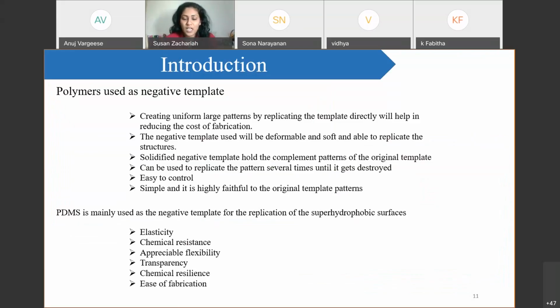To make a structure similar to the lotus leaf, first we need a negative template that can take the structures of the lotus leaf and give them to the polymer coating that we use for the cold rolled steel. A negative template takes the complementary structures of the lotus leaf. So if the lotus leaf has peaks, then this negative template will have holes. When we place this negative template on the polymer coating on the surface, we get the actual structure of the lotus leaf on the coating applied on the cold rolled steel.